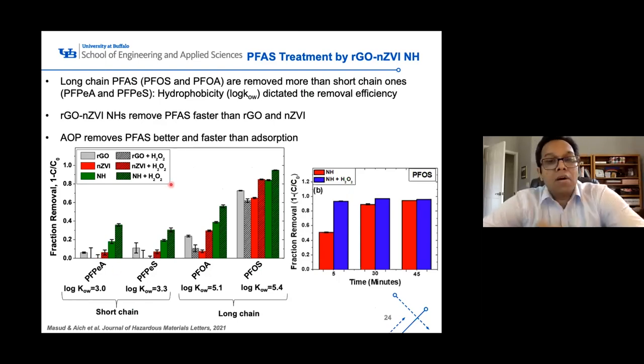So first, what we have done is we looked at the fraction removal of different PFASs using these different materials. On this side, you see without hydrogen peroxide, and on this side with hydrogen peroxide. Basically what we saw is that if you look at the removal percentage, the long chain PFASs are mostly removed, more removed than short chain PFASs. This five carbon one was very less removed, like 40% at best. On the other side, we got the highest, 95% removal, with the PFOS. PFOA is not that much, 60%.